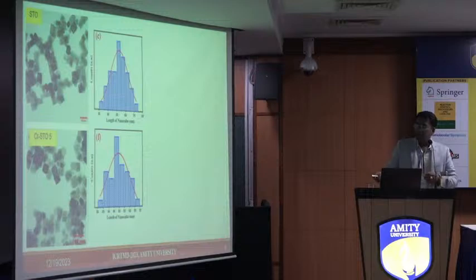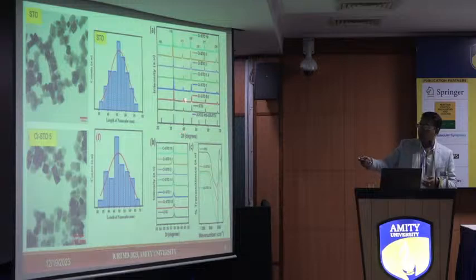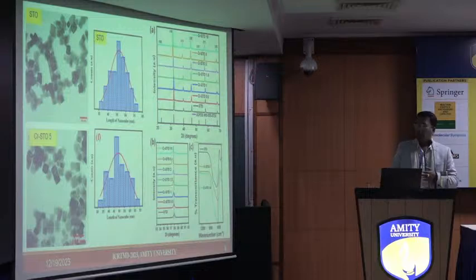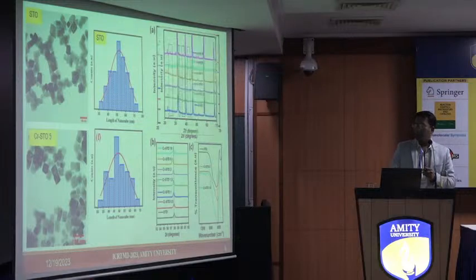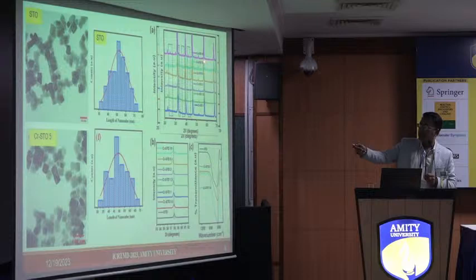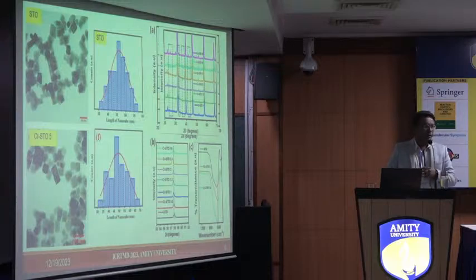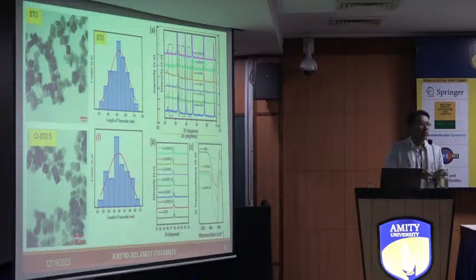So for that we prepared chromium-doped strontium titanate samples for different concentrations, and what we found is that as we change the concentration, there is a peak shift, which is clearer in this image, okay? A slight shift suggests that there is doping of the chromium. If we increase the dopant concentration, let's say 15%, then you will see that additional peaks are also appearing, which is suggesting that in addition to the chromium-doped strontium titanate, you have formation of some other phases, which is not required because we wanted to study the effect of the chromium doping.